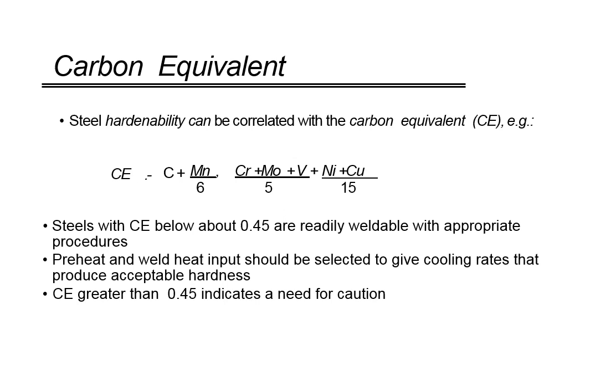Carbon equivalent. This is something that's going to come into play in regards to both preheat and post-weld heat treat. We keep talking about chemistry, and this is how we figure out our carbon equivalent, using this little equation. Steels with a carbon equivalent below about 0.45 are readily weldable with appropriate procedures. So if you've got a material and you crunch your numbers and look at your chemistry and it comes out below 0.45, you're probably not going to have problems with it.